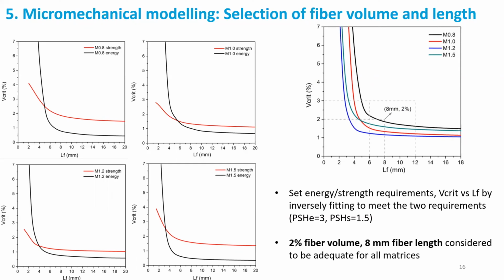As you can see here, for both the black curve and the red curve, the points on the curve are the critical values to meet both requirements. And the area above both curves is the one suitable for selection, which meets both PSH requirements. Since we want to choose the fiber volume as low as possible, to reduce the cost and to avoid further mixing problems in the future, finally we choose the fiber volume at 2% and fiber length of 8 millimeter for all matrices.